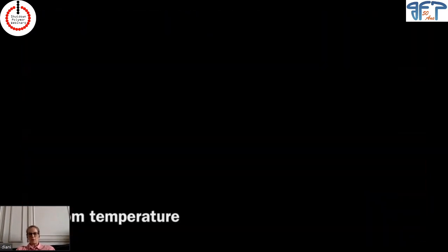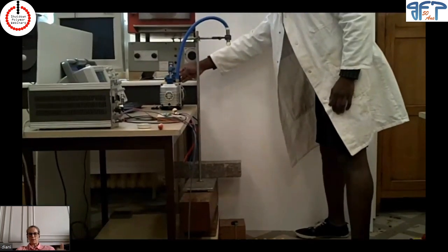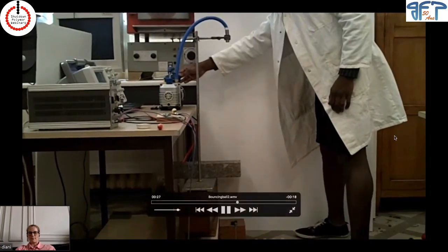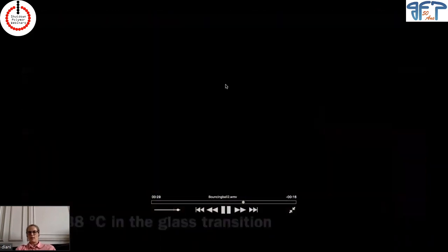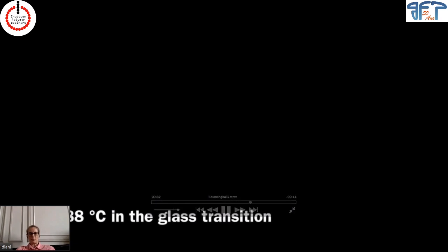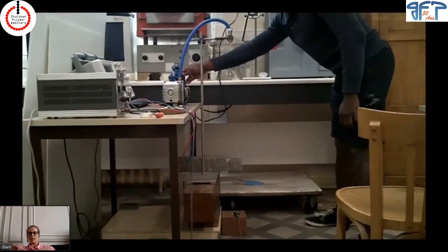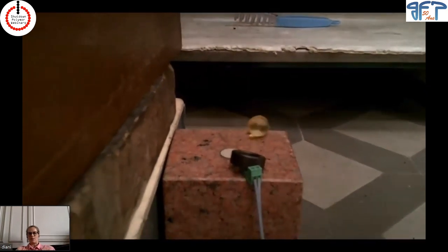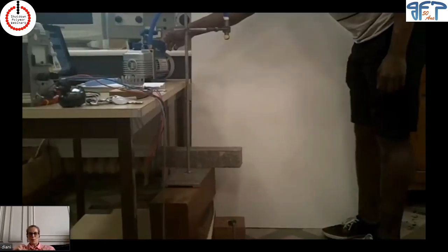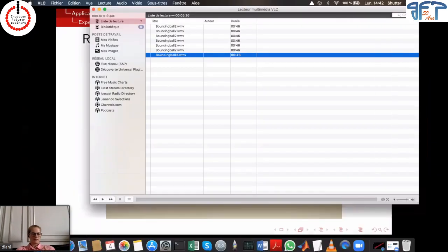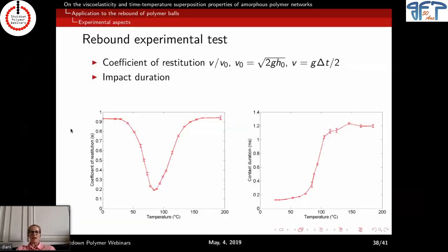So at room temperature, basically the material is in glassy state, and you're going to see it coat the ball here, so it's a really good rebound. At 88 degrees, we are within the transition, and there is almost no rebound. It's very small. And at, I don't remember the temperature, but the high temperature in the rubbery state, we had very good rebound.